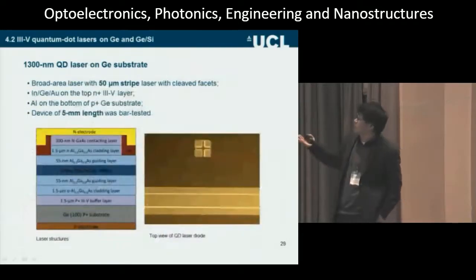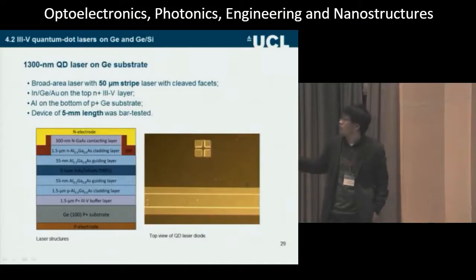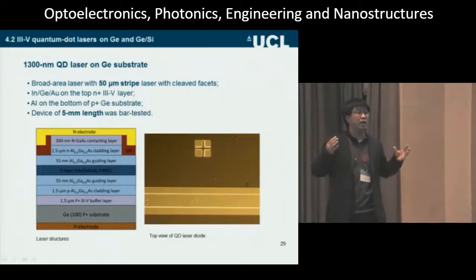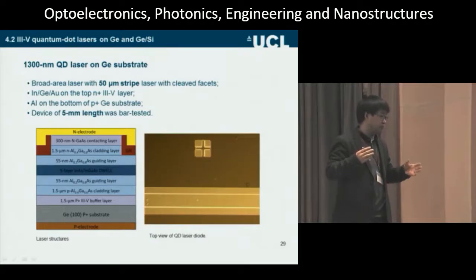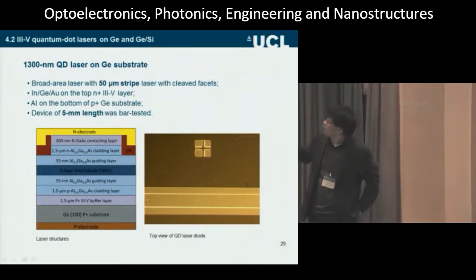With these results, we worked with Sheffield at that time. We put III-V quantum dot lasers on germanium. So this one, I have to say, guys, the majority of devices I show here are very big. It's only for scientific reasons, not for very practical application. This device is a broad-area laser with a 50 micron stripe and very long, 5 millimeter long. So we make the P contact at the bottom, n contact at the top.